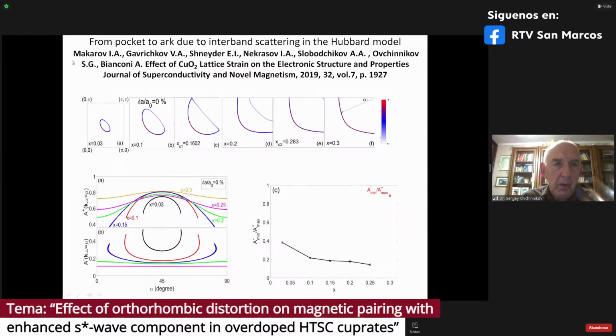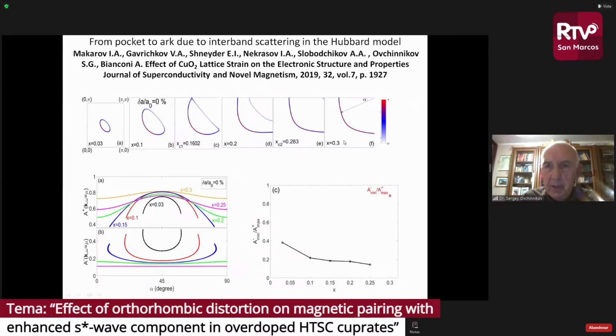And for small concentration of holes, we have a small pocket. Then the pocket becomes larger, and finally it crosses the boundary of the Brillouin zone. And then this inner part has small spectral weight. This is the so-called pseudogap effect. And finally, in the large doping, we have a standard Fermi liquid, a Fermi surface with only one surface, without any pseudogap.